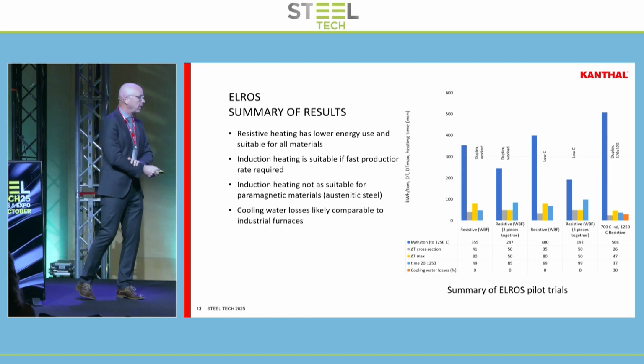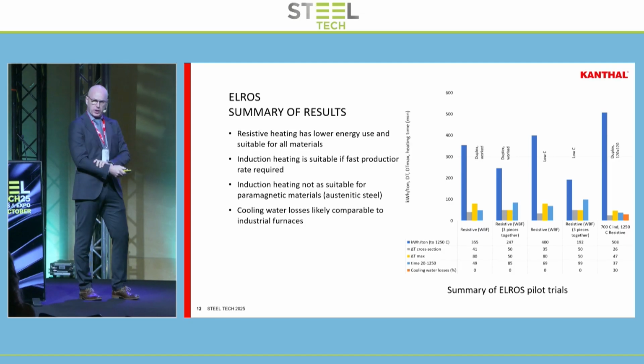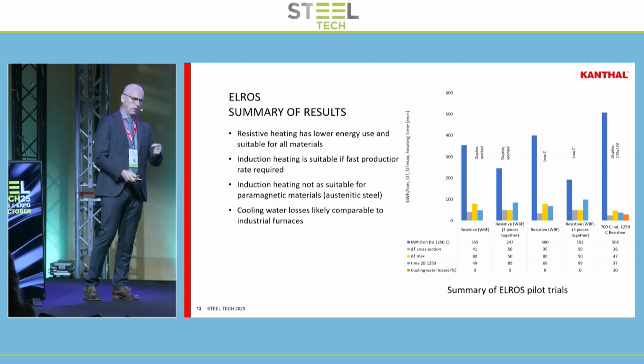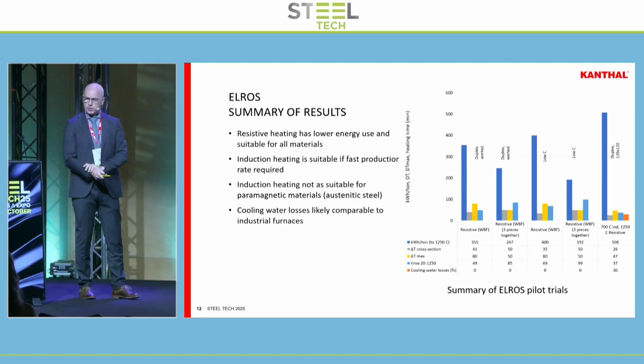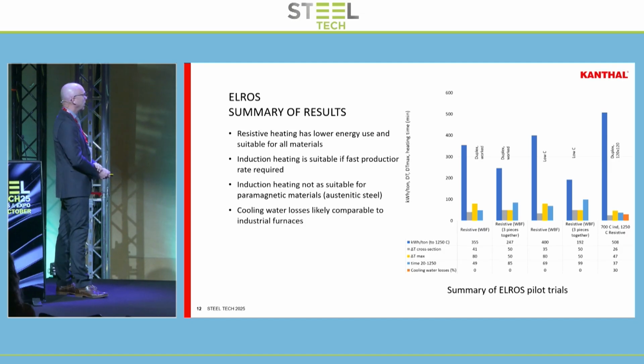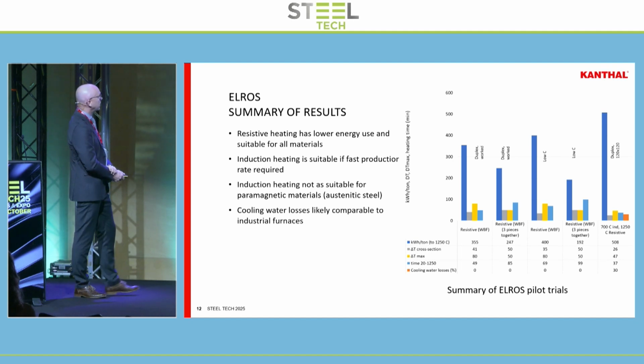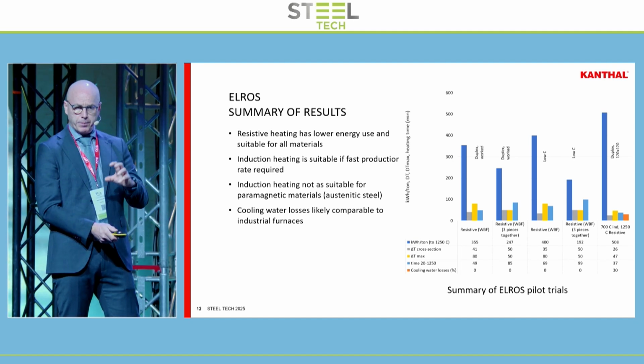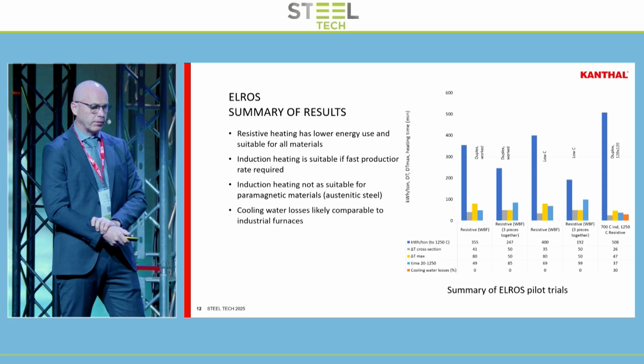One maybe drawback from induction heating is you have to have, of course, a cooled coil, and there's some energy losses involved there, so it's a little bit different energy balance than you have with resistance heating. But all in all, we show that resistance heating has good energy efficiency, even for reheating furnaces.